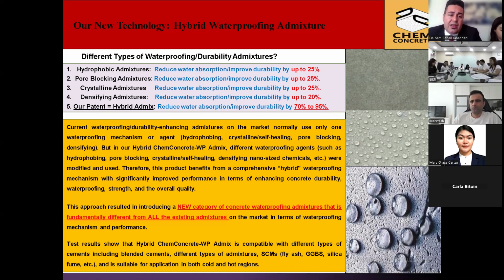But our patent and our technology is a new category of concrete waterproofing admixtures, which is called hybrid admixture. And independent testing has proved that this hybrid admixture can reduce water absorption and improve durability by 70 to 95%, depending on the dosage used.